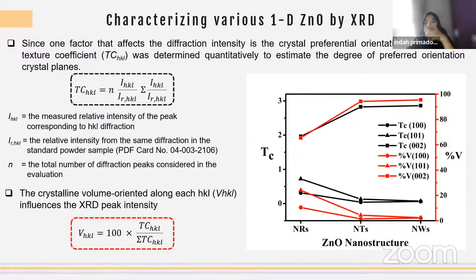I picked three peaks to be considered in this calculation. The three highest peaks are 100, 101, and 002. The TC value is the black line here. So you can see that for 002, the nanotube and nanowire are comparable, a little bit higher for the nanowire, and the lowest one is the nanorod. So this is in agreement with the SEM result.